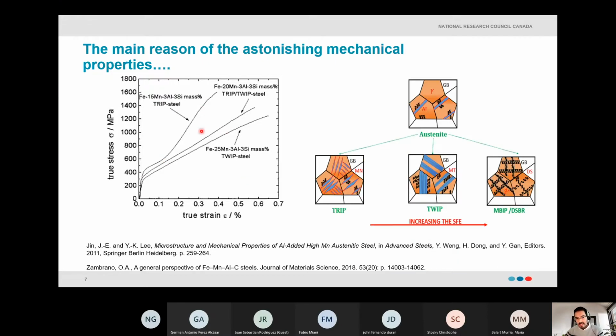The reason behind that is that with this alloy, we can control the chemical composition and the stability of the austenite. Basically, what I mean by austenite stabilization is we can control the chemical composition to make the austenite less stable or more stable. And that is reflected in different deformation mechanisms. If we make the austenite really unstable, we can promote the transformation from austenite to martensite. If we make it more stable, but not too much, we can favor the formation of mechanical twins. And if we make it too stable, we will have the formation of microbands made of dislocation arrays. These are special deformation mechanisms that we can control by the chemical composition and temperature, and this will determine the mechanical properties of this material.